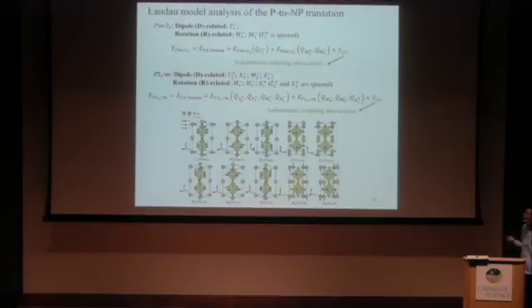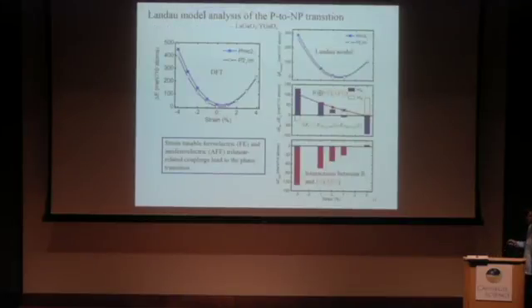And in the Landau model, we have 3 parts. The first, which the terms only consist of the polar or antipolar mode, and the second, the terms only consist of the tilt and rotational mode, and the last term only consists of the interactions between the first 2 parts. And the figure is just describing the mode displacement. By comparing the phase diagram from the direct DFT calculation and also the Landau model, we found that this shows the similar tendency of the phase stability, but there is a difference here. We found that the phase transition occurs at 2% tensile strain, versus no transition occurring in this DFT phase diagram.